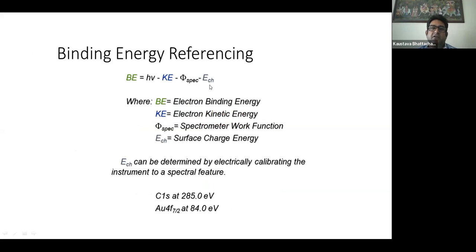First of all, we can think of a generic material, which can have a surface charge also. So its overall binding energy will depend on the energy given by the X-ray, minus the kinetic energy of the electron, and phi, the work function of the spectroscope, and also it will depend upon the surface charge. If my Ech is not 0, then my surface is having a charge. That charge will definitely have a part to play in the binding energy. So if the surface is already charged, then we need to deduct that surface charge from the binding energy to get the exact binding energy of the material.